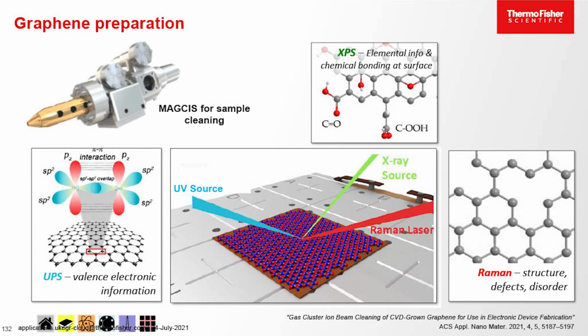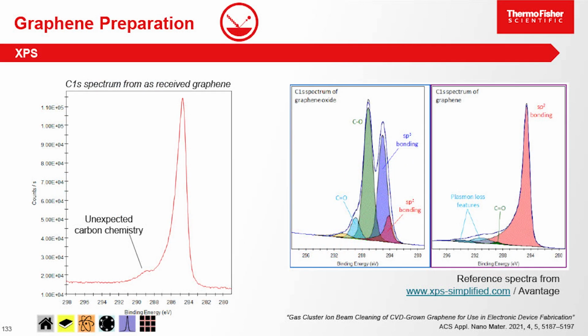samples to use in devices, how you can determine, once they've been transferred from the growth medium onto a medium you're going to actually use to prepare the device, how you know that that's been successful and you've got a clean surface. And to do that, we're using XPS, obviously, to check the chemical state of the material. We're using UPS to check the valence information, as we just saw with the PFO. And we're also going to use Raman spectroscopy to understand the quality of the graphene film that we have at the surface.